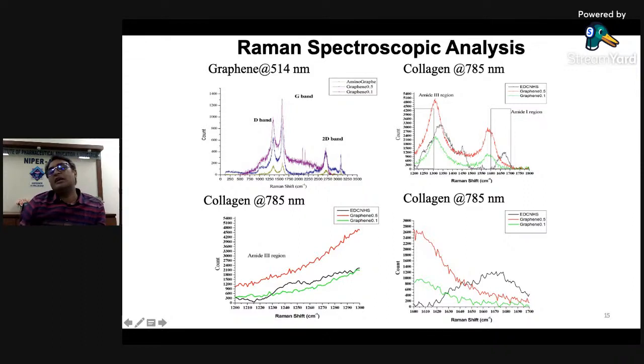This amide 3 and amide 1 region represents the helical region of the collagen, and you see more helical content is present in 0.5% graphene, shown by the red graph here. We further zoomed into this area, and we found the amide 3 region is significantly higher, showing that more helical content of collagen is retained or promoted in 0.5% graphene incorporated collagen hydrogels.